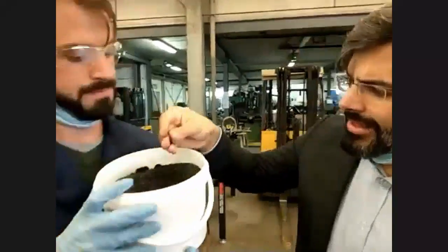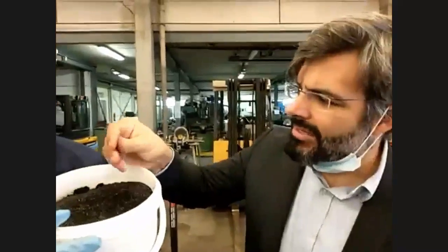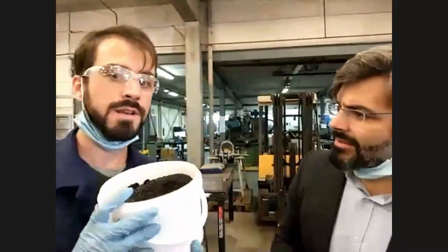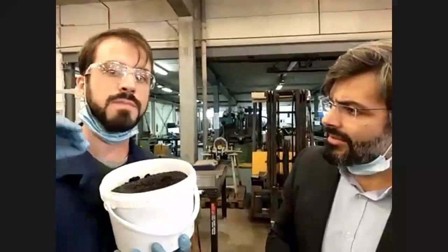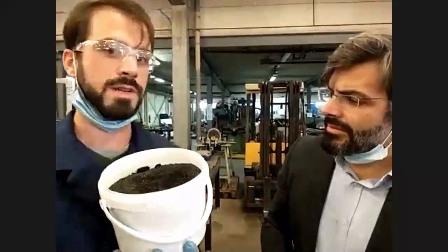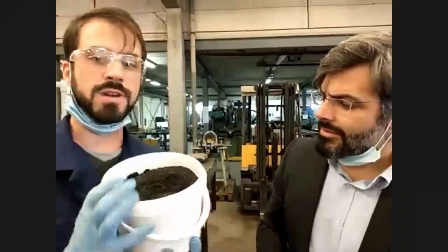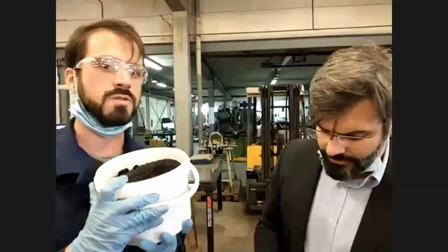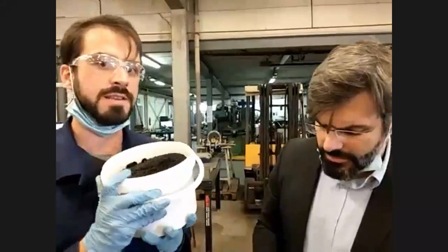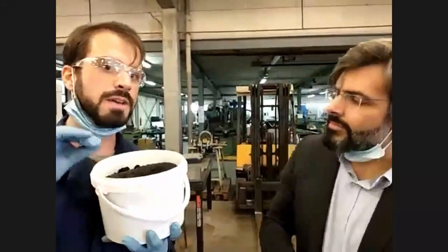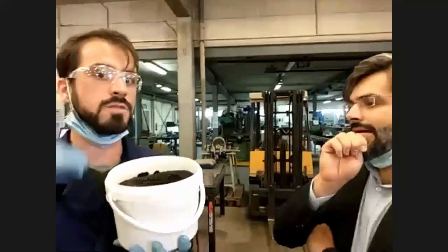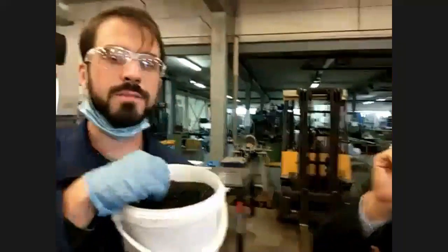Tobias, doesn't that look like a bit like copper slag? Actually, it is relatively similar to copper slag. So we try to actually make a kind of copper slag out of the red mud. As you mentioned correctly, we have a similar chemistry in the bauxite residue and in these copper slags. So we basically try to mimic this copper slag in chemistry and also in mineralogy. And what we get is something like this.